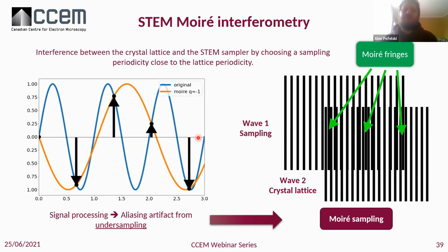I won't go into all the details of that. I just try to give an intuitive approach, and I really advise going to the articles if you want to know more. But the idea is to make an interference between the crystal lattice and the STEM sampler, because these two elements are periodic. So if you choose a sampling periodicity that is close to the lattice periodicity, you will be exactly in the configuration described before. Wave 1 is the sampling, wave 2 is the crystal lattice, and we generate some Moiré fringes.